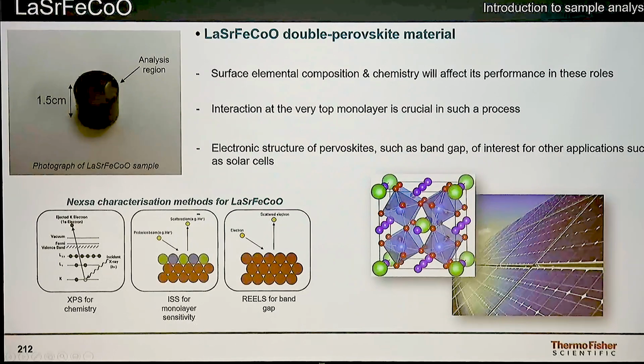Okay, so moving on from 2D materials to more three-dimensional complex ones. So lanthanum, strontium, iron, cobalt oxide, a double perovskite material with hopefully applications for solar photovoltaic materials. What we want to do here is check the chemistry as usual, but then look and see whether the surface is the combination of elements that we expect using ISS, and also look at the band gap using REELS.